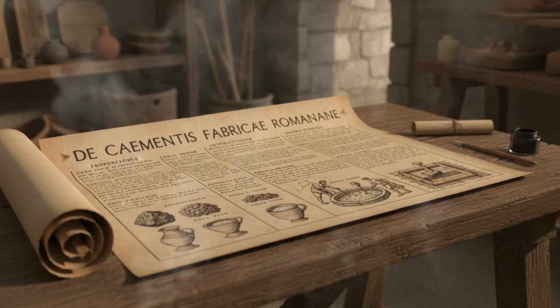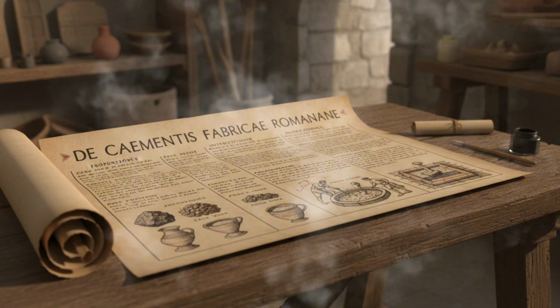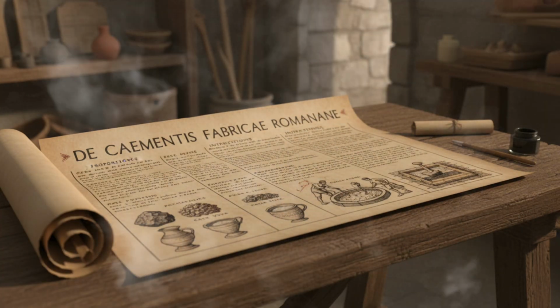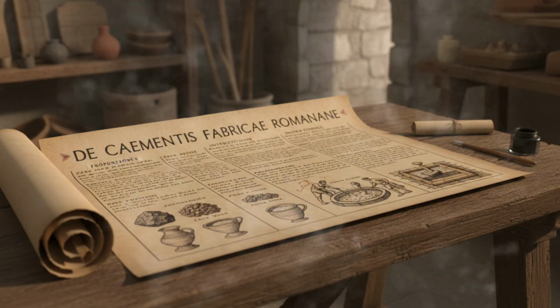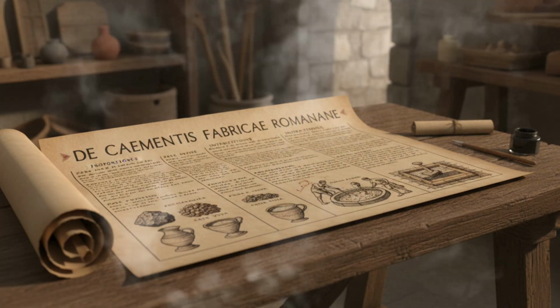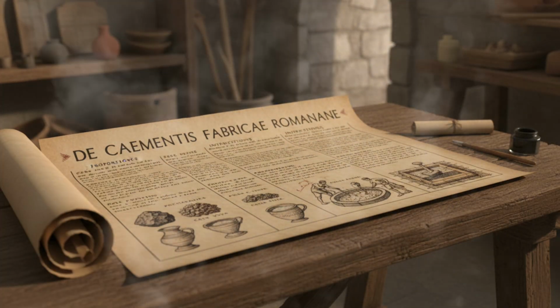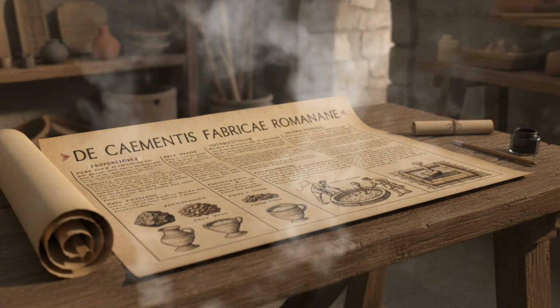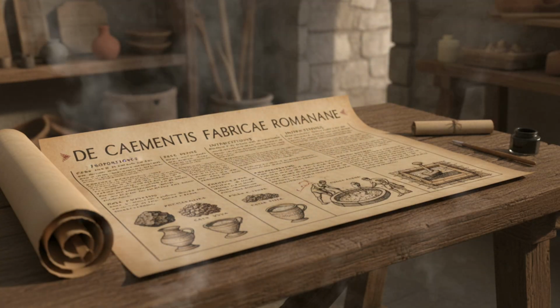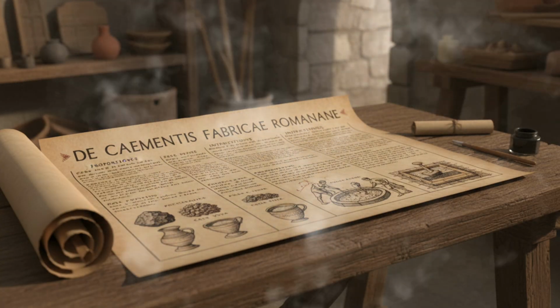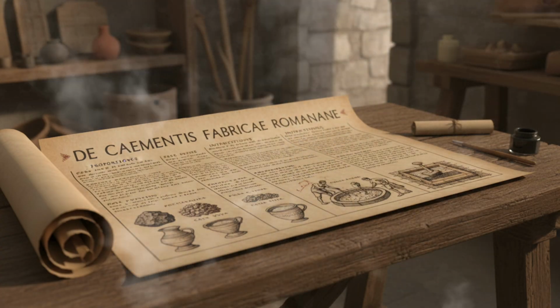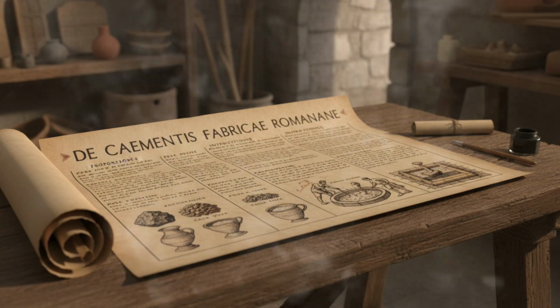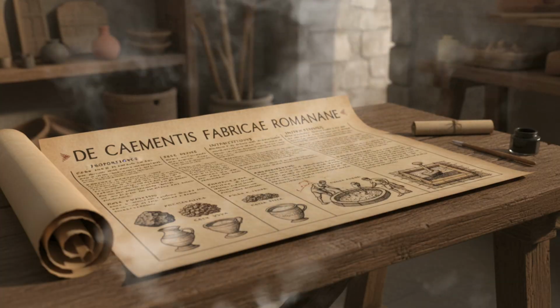In Bath, England, Roman engineers built pools and channels handling hot mineral springs. The concrete had to resist not just water, but high temperatures and aggressive chemical conditions. They succeeded by adjusting their standard recipes, creating material that survived conditions that destroy modern pool concrete. Analysis shows they used a higher proportion of lime and selected aggregates that remained stable at elevated temperatures.